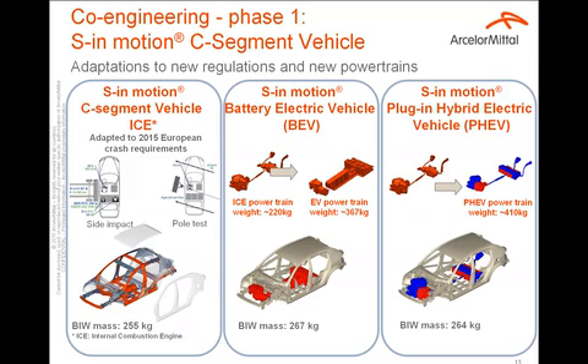So we achieved a very light body-in-white proposal at 255 kilograms for ICE powertrain on this segment, taking into account all new 2015 European crash requirements. And then we had this solution to two new powertrains, battery electric vehicle or plug-in hybrid. And we have shown that only 10 or 12 kilograms at maximum is enough to cope with the higher power, the higher mass of the powertrains that gives some additional constraints in the load cases and in the performance of the vehicle.